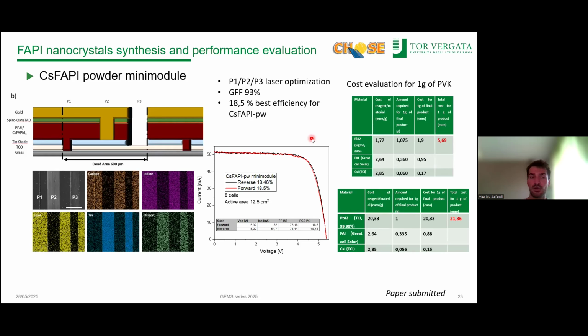We also performed a small cost evaluation for 1 gram of perovskite produced with the high purity precursor lead iodide, and the other one with the standard Sigma 99%. And as you can see, even with the yield of the synthesis that is not 100% in the case of low purity lead iodide, the cost is 1/4. The cost of the high purity perovskite is 4 times more than our perovskite made with low purity precursor. That quite well demonstrates that it's not a big requirement, let's say, to get good and high efficiency.